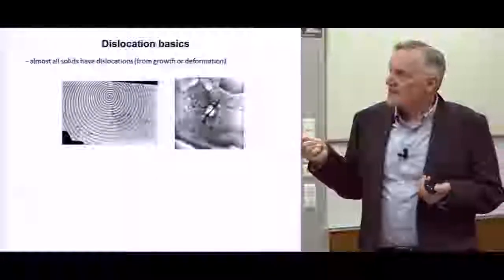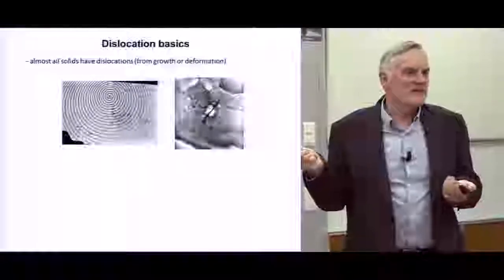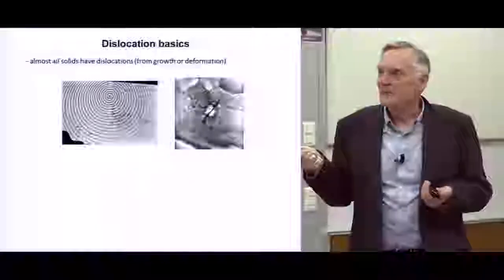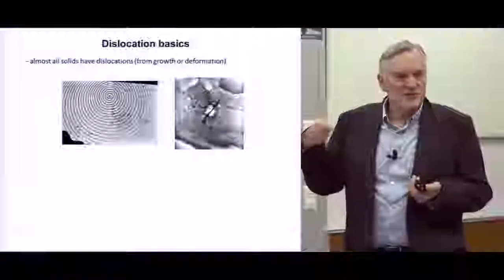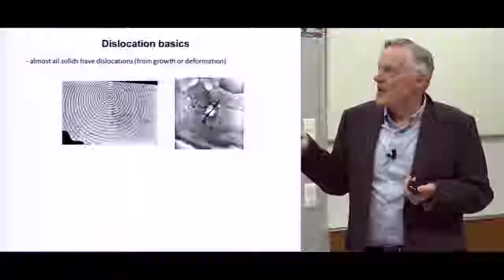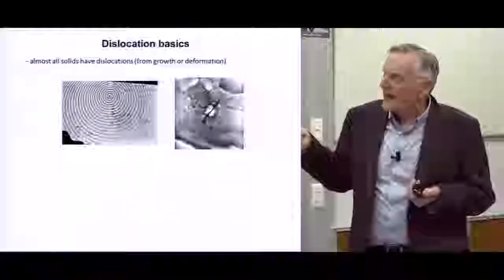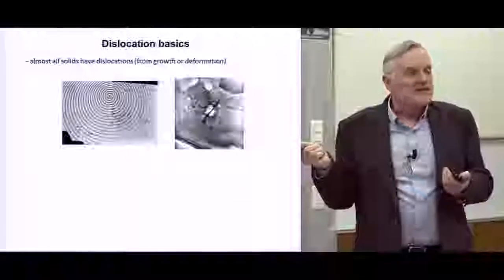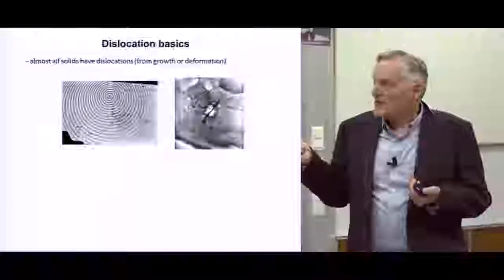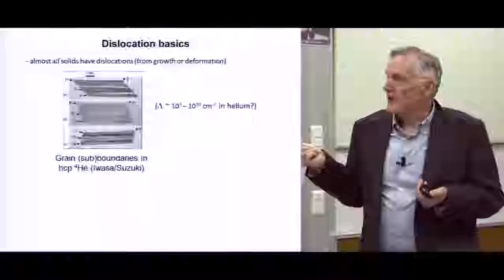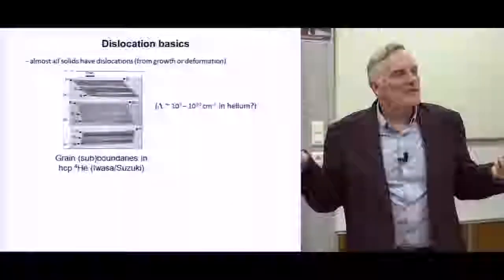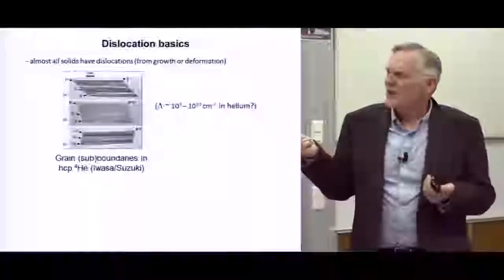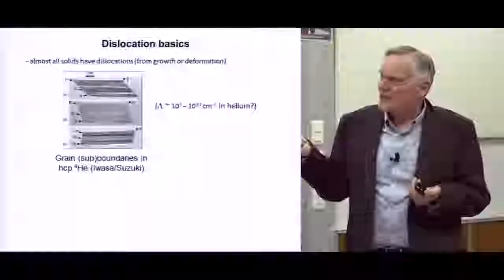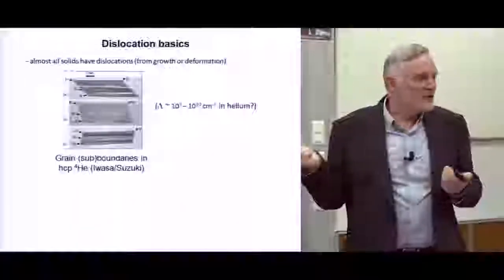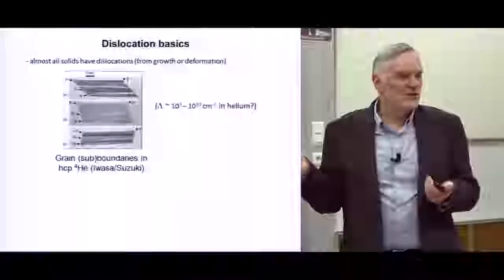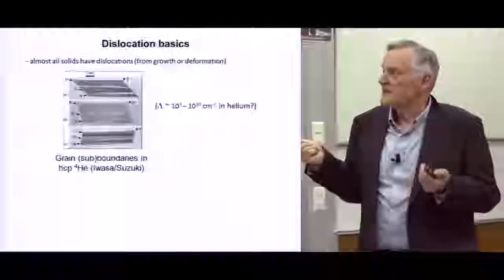And so just basics about dislocations: any crystal has them. Maybe they only have one if you're really lucky. In growth, screw dislocations help you grow, they give spirals. More often, if you indent something, you get a whole tangle of dislocation lines. They're lines, kind of random. These are imaged in a transmission electron microscope. You can't do that in helium, but you can put them in a synchrotron and do an X-ray image. You can't actually resolve individual dislocations, but you can tell there are areas where there's lots of them. So there are dislocations in single crystals of helium as well as in everything else.